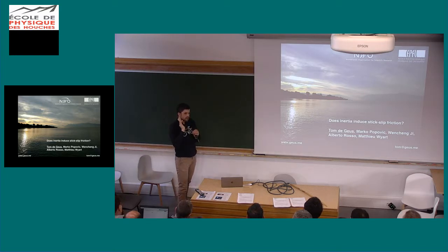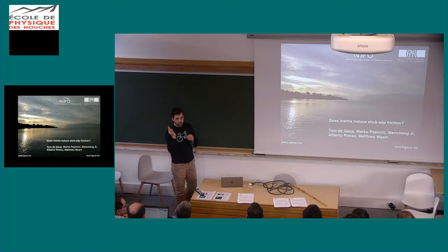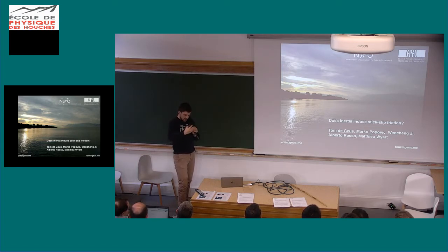Now, if you ask, does this picture also hold in an amorphous solid? Because I think that is what you're asking. The answer is maybe. There could still be this nucleation picture. But then it depends, I think, largely on how compact or not these avalanches will be. So this nucleation was there because these avalanches are relatively compact. And inside this compact object, there was a lot of mechanical noise going on, and that locally weakened me, and that allowed me to nucleate something bigger, which had a clear bubble in 3D or just a clear front in 2D.